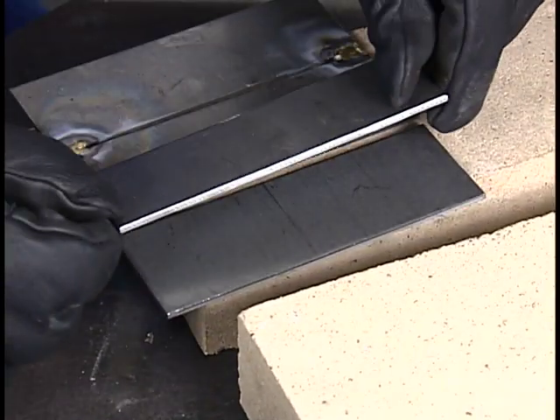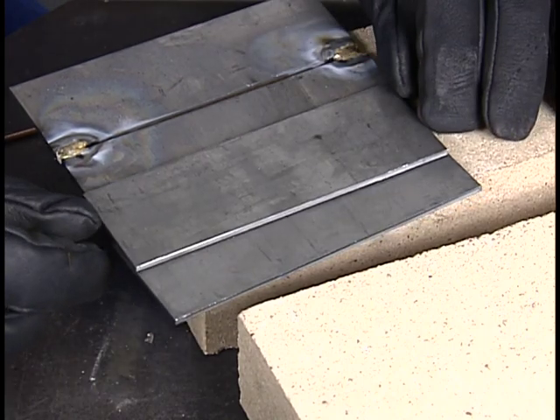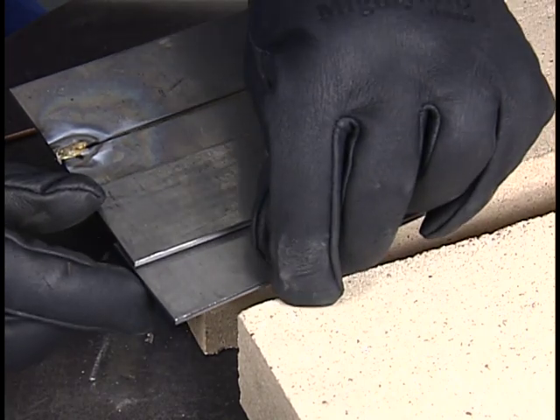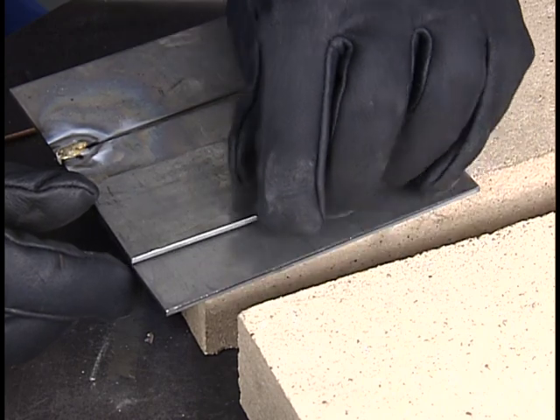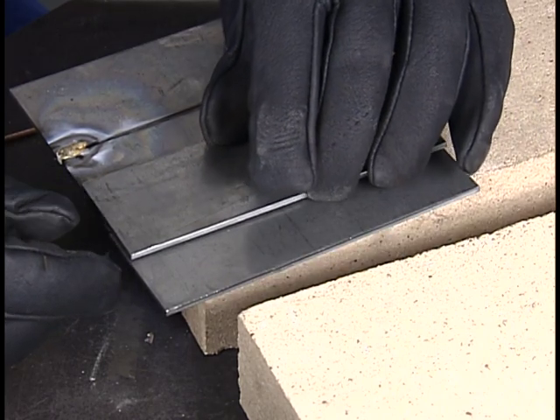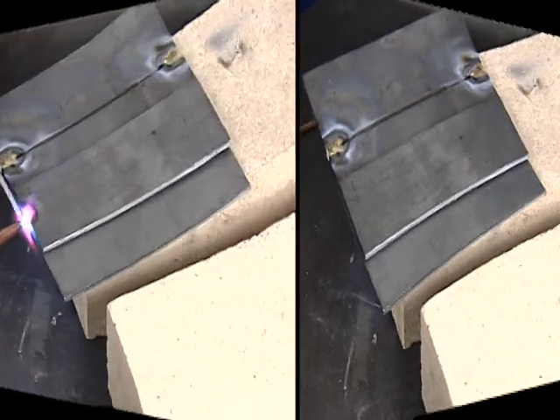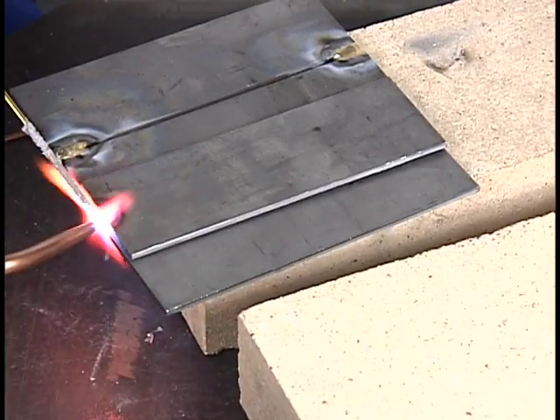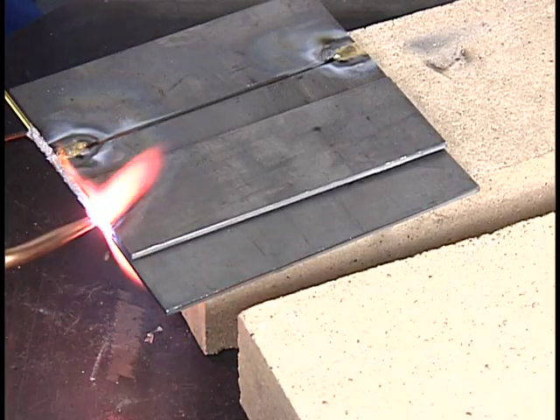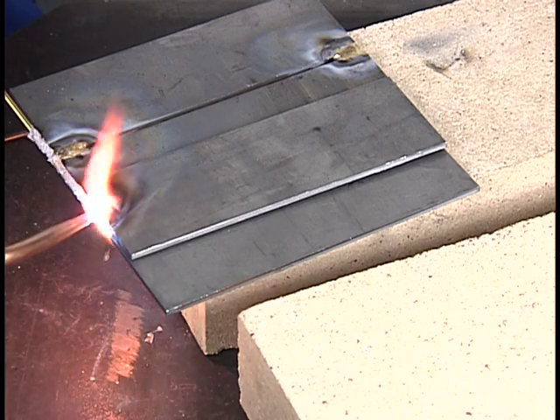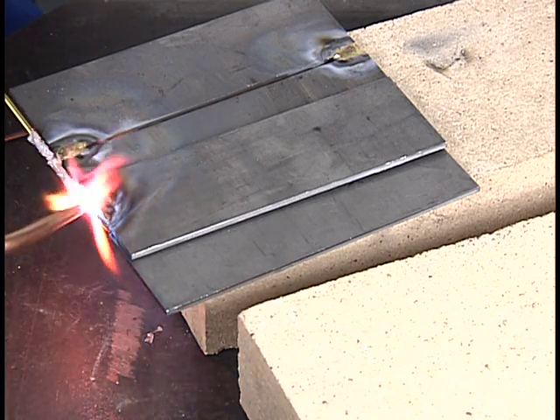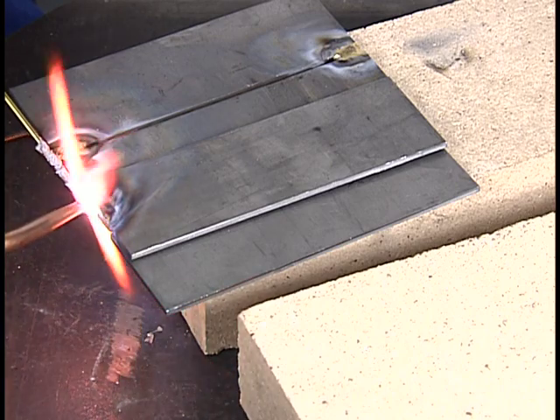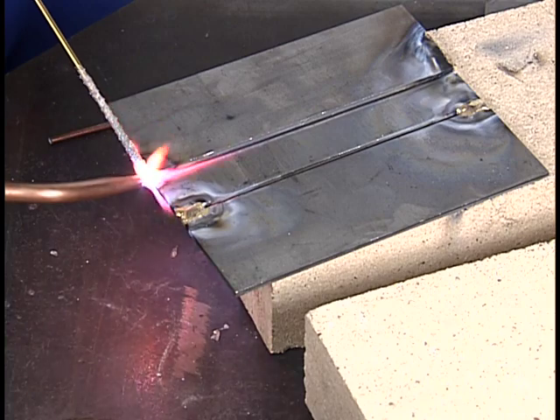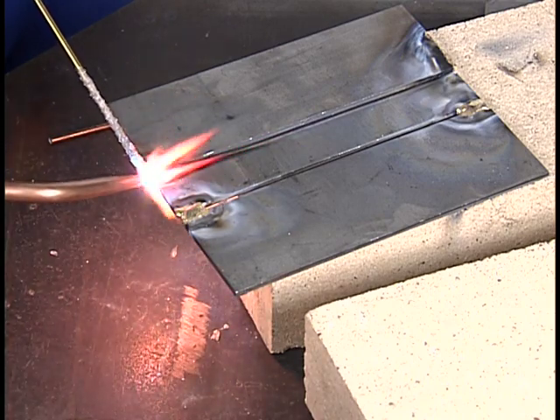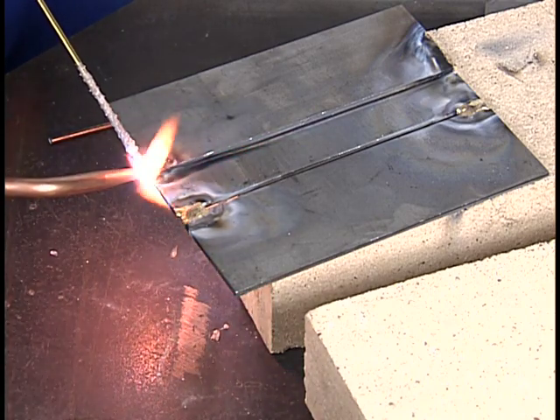After tacking the butt joint, turn the workpiece over and position another plate on the workpiece to form the lap joint. It should overlap approximately 1/2 of one plate. Use an extra plate underneath for support. With the flux-coated rod, deposit a 3/8 to 1/2 inch long tack weld at one end of the plates. It may be helpful to use a slight torch motion to improve control of the puddle. Rotate the plates, then deposit a second tack weld that is approximately 3/8 to 1/2 inch long on the opposite end.